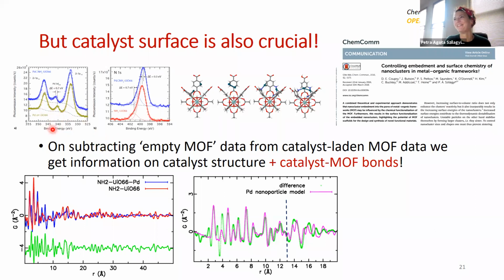For the others, it's more oxidized, but it's still not. For example, we did an in situ EXAFS study while reducing the precursor. We used a palladium 2 precursor added to the framework. We looked at it while ramping up the temperature, and we definitely see a change in the oxidation state as it gets reduced.